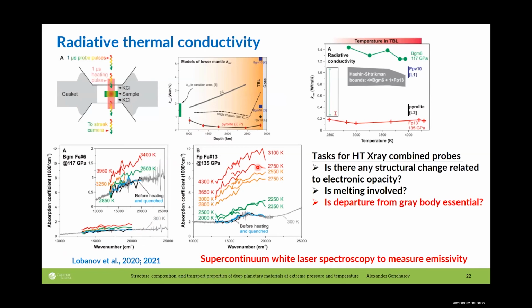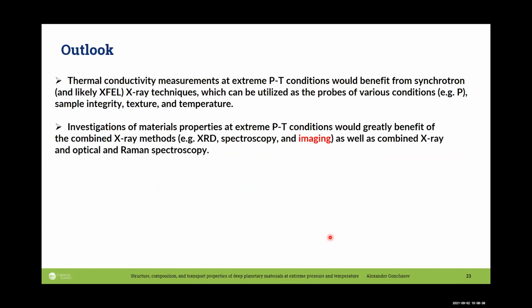Once we can measure the absorption spectrum, we can measure the reflectivity spectrum. And once we can measure reflectivity spectra, we can address the question of wavelength-dependent emissivity, and so we have all this technique in place, so we can address the question of gray body approximation. So essentially, I described a number of techniques which have been done already in my lab, using various X-ray diffraction and other techniques. And what I'm trying to say is that thermal conductivity measurements could be improved if we combine them with the various X-ray techniques.